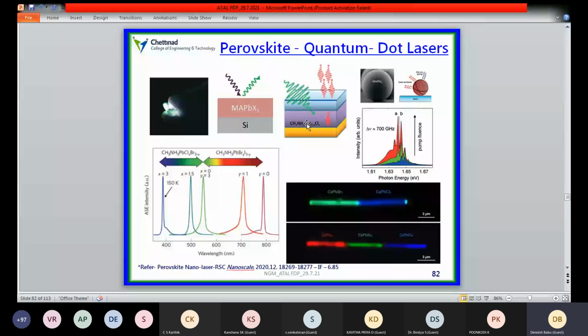So instead of these high cost elements, very low cost materials like methylammonium lead halide systems and other materials are also useful. It is suggested that these materials are also able to exhibit light emission, so they will be useful for laser applications also. These are some rods prepared and deposited on an FTO substrate, and under a UV lamp they exhibit blue, green, and red luminescence.